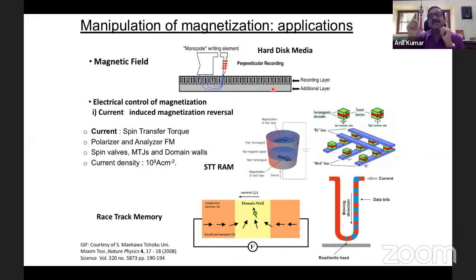If you remember the hysteresis loop I showed you, if I apply plus H magnetic field, which is higher than the coercivity, it is in the plus M state. That means magnetized upwards. Now, if I apply a magnetic field in the minus H, in the negative direction, more than the coercive field, then the magnetization switches down. This is what is happening in your computer hard disk.